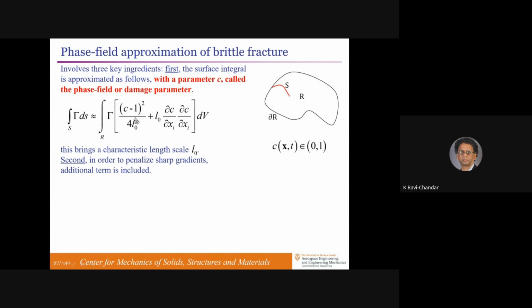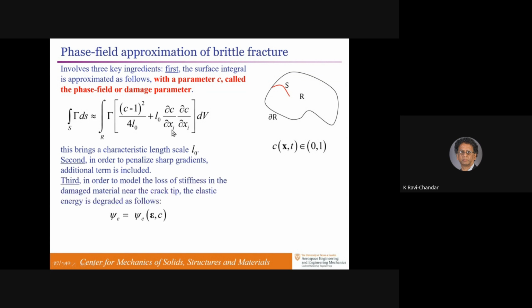This brings in intrinsically length scale dependence, so they've introduced a gradient penalty term to penalize sharp gradients. And finally, to model the loss of material stiffness, you degrade the strain energy in the material based on some assumption on how the damage progresses as well.